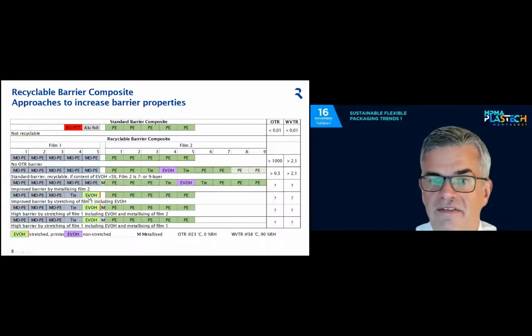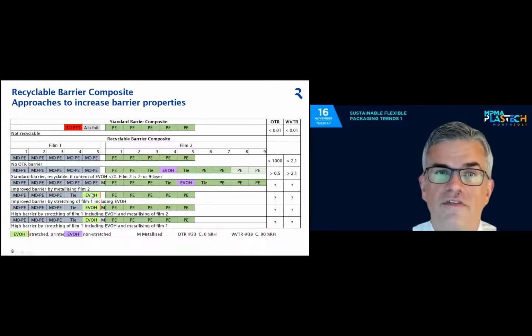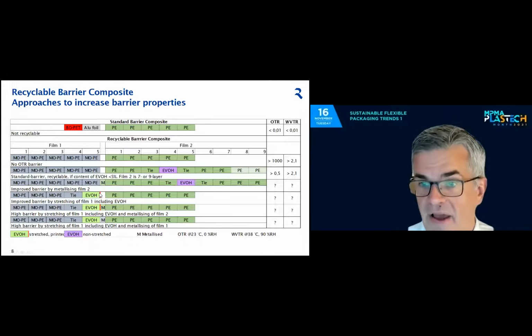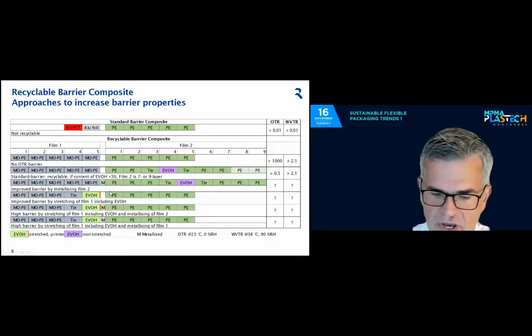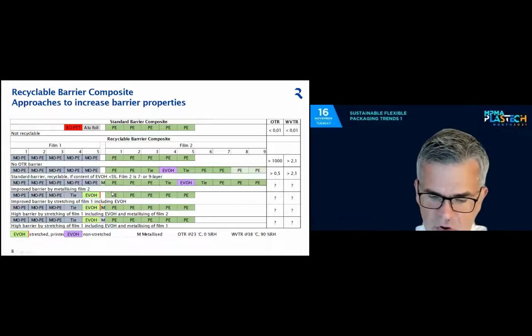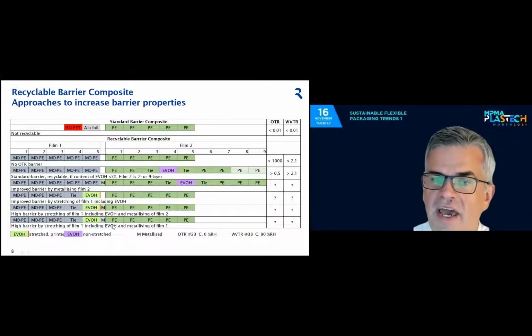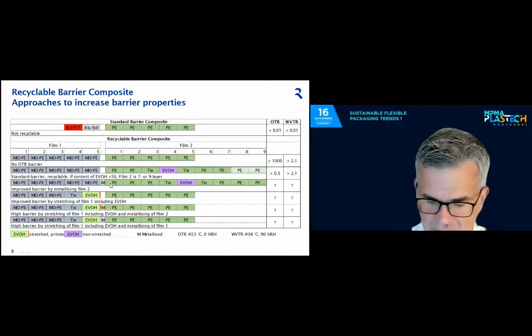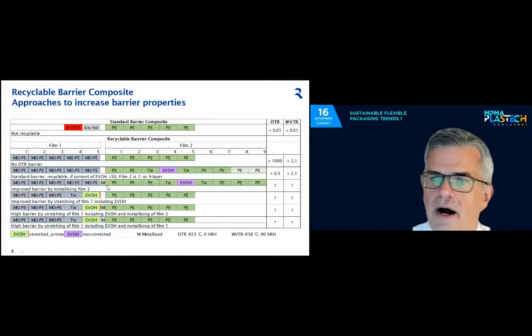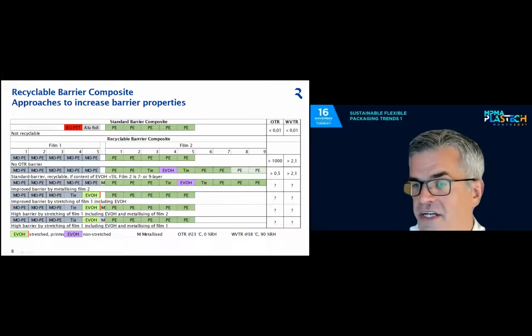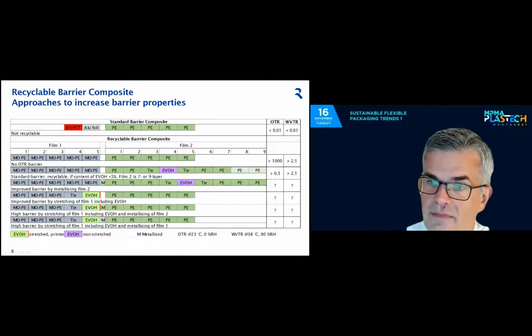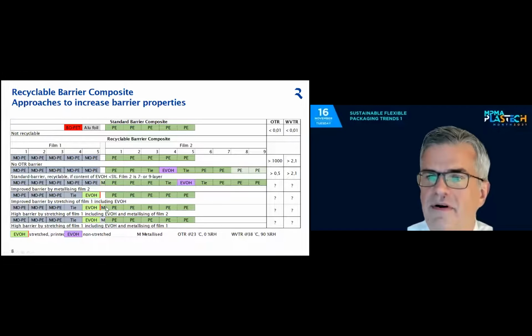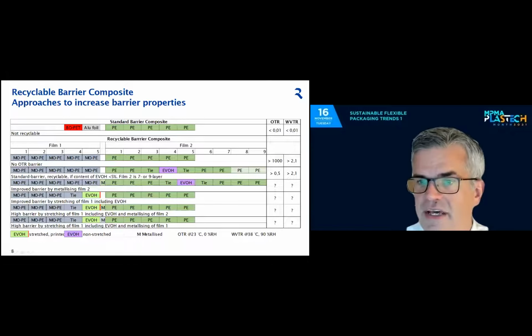Another solution is taking my stretched PE film and adding EVOH, either in the center, but I can use it also in the outer layer. If I do so, I have to take care of the moisture in order to avoid water absorption. I have to print the backside by rotogravure completely. And the lamination film would be, in this case, a standard lamination film. And to go to the next step, I could even metallize this standard lamination film.